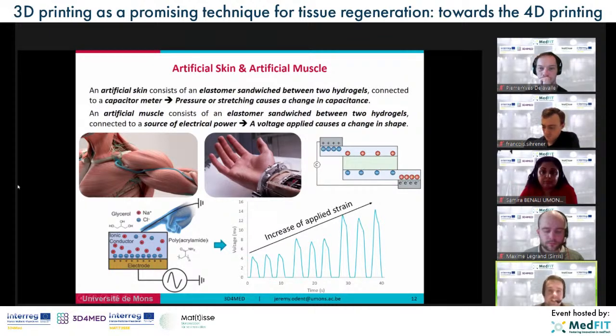So we actually use our systems in touch sensing applications up to now. And the 3D printed ionic hydrogels will generate here, as you can see on the graph, an output voltage in response to any mechanical deformation. And this is related to the mechanism of ion redistribution. It's also interesting to see that the generated output voltage amplitude is found to be totally linear with the imposed mechanical deformation, as you can see here.